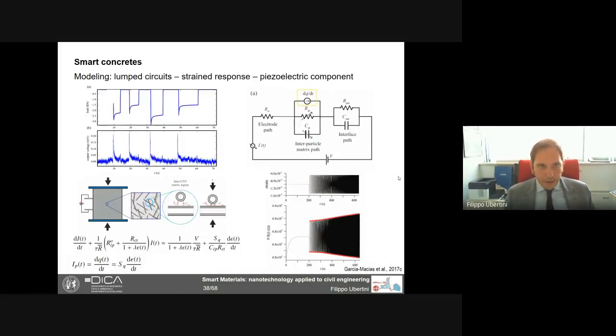So a few years later, with Dr. Garcia, in another paper, collaborative papers with the rest of the group as co-authors, we proposed, let's say, an enhancement of the previous model, where we have noticed this. We have noticed that these materials, besides having a very strong piezoresistive behavior, they also have a little bit of piezoelectric capabilities. So if we look at the specimens and we apply a load, we see a change in voltage. We see the material outputting a voltage change, so without any external input. So this means that the material is a little bit piezoelectric.